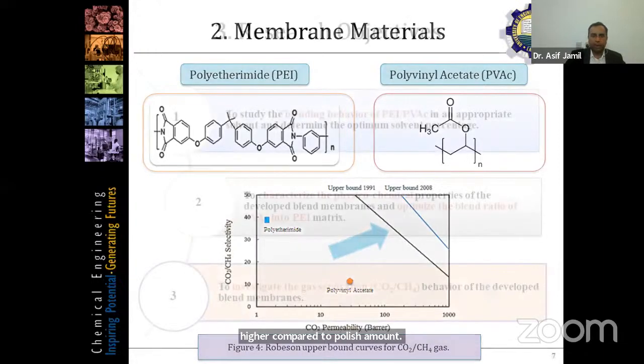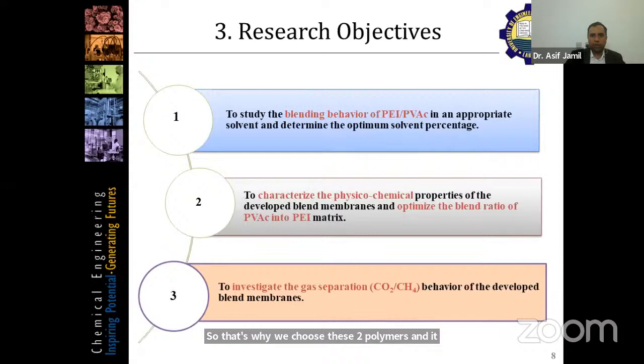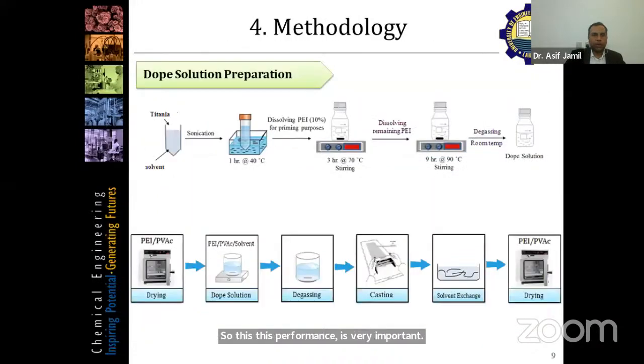The research objective is, first of all, to optimize the solvent that we used, and then the physicochemical properties, so that we can optimize the blend ratio of PVAc into polyetherimide. Since we are using it for CO2/CH4 applications, this performance is very important. For the methodology, we dissolve polyetherimide in NMP at almost 70 degrees Celsius, and later we add polyvinyl acetate so that we can form a dope solution.